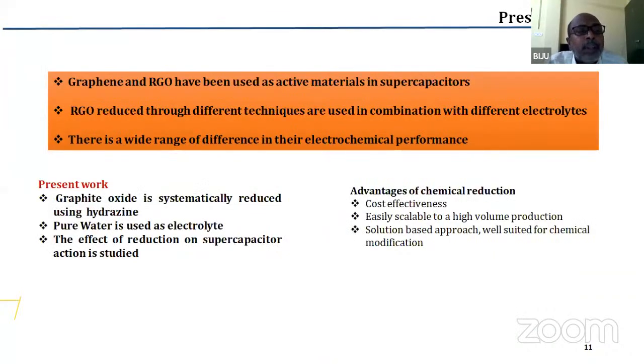Now, in this work, what we have done is we have used a properly synthesized, systematically reduced graphite oxide or graphene oxide as an active material, and we have used pure water, actually HPLC grade water, as an electrolyte, and the effect of reduction of graphite oxide on the supercapacitor action is studied.